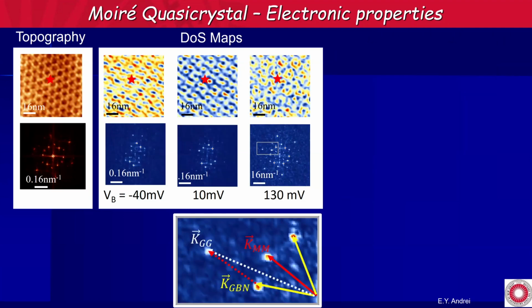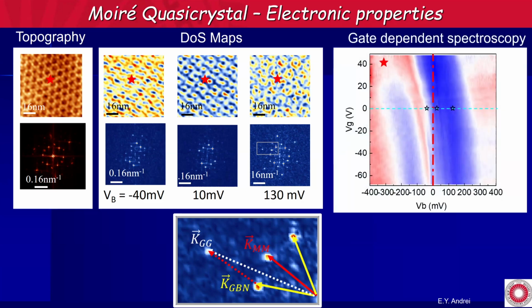And then we can do the same for our quasi-crystal. Again, the symmetry is completely lost. Every different energy has different symmetries, because the wave function now scatters off a non-periodic potential. So there are all sorts of interference, destructive and constructive interference. Now when we look at the spectroscopy again, it's very, very different. Maybe we have a gap, but maybe we have a flat band. Now we have dozens of samples and regions with different quasi-crystals and intercrystals, and the band structures are crazy. And I'm not sure I'm allowed to call this a band structure.